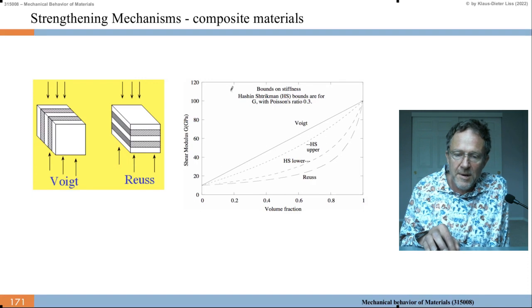And then there exist other models like the Hashin-Shtrikman bounds for G with Poisson ratio 0.3. So we haven't put the Poisson's ratio in, we haven't put the shear modulus in. They play a role, of course. If you compress here, you also get a lateral expansion due to Poisson's ratio. And this is different in the white and in the black layer. So that is where Poisson's ratio plays a role. And then when you have a difference in expansion between the white and the black, you get a shear between the white and the black. And that's where you get the shear modulus in.